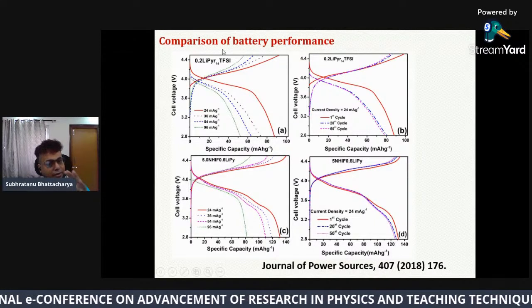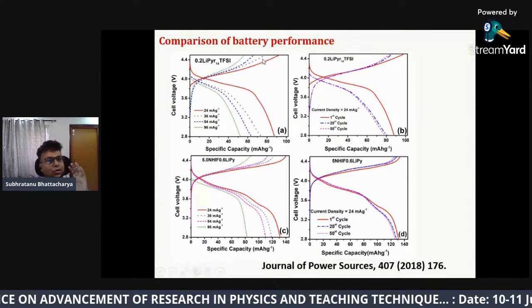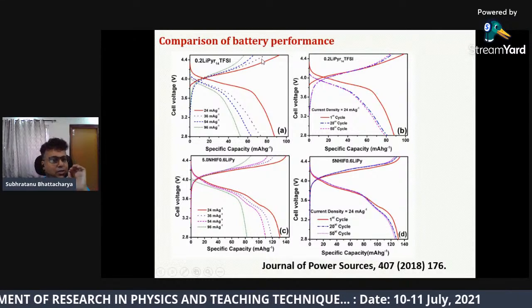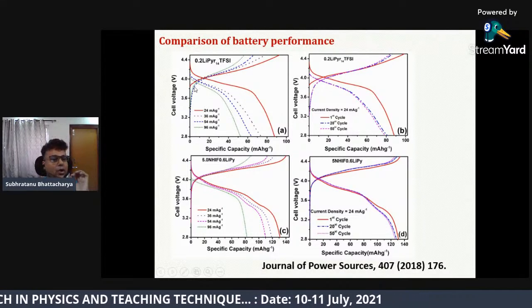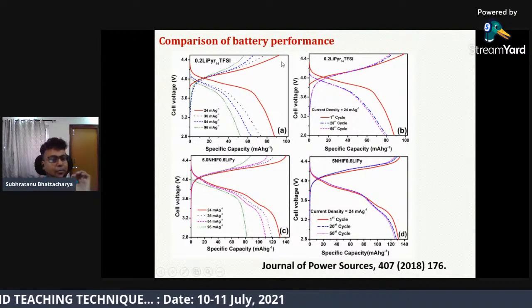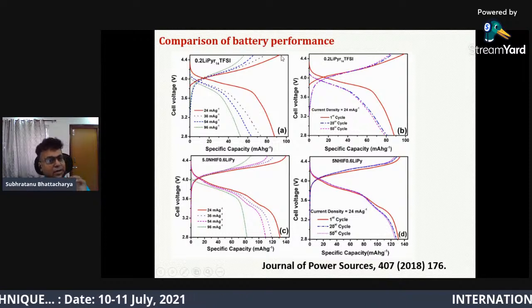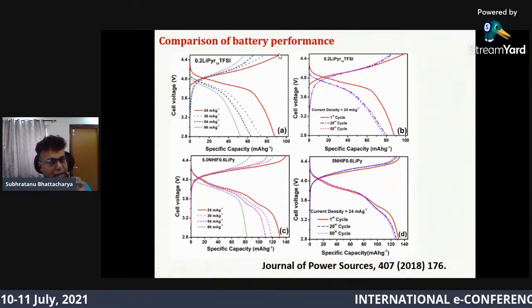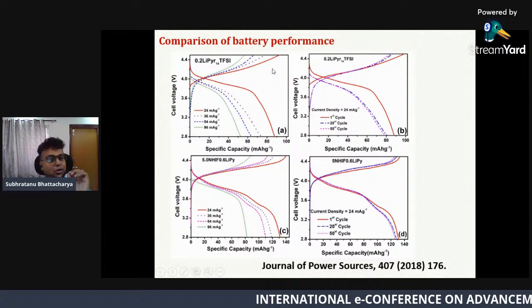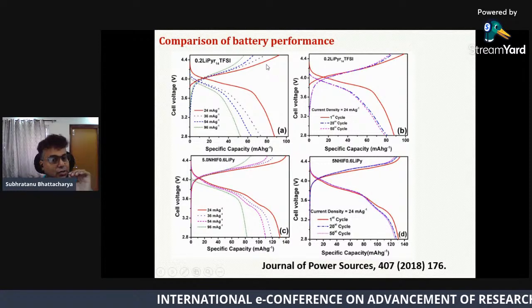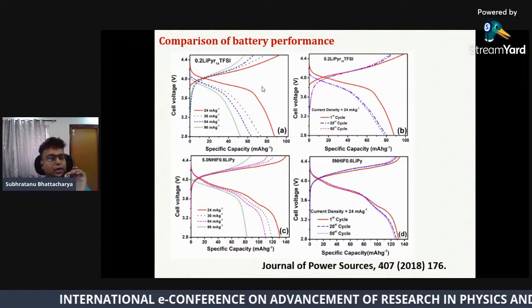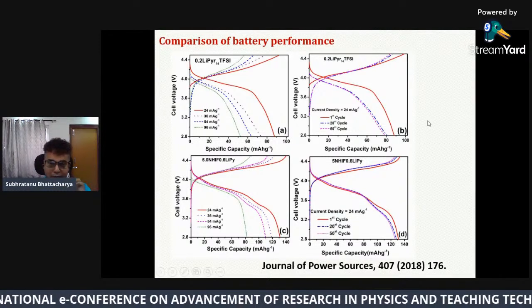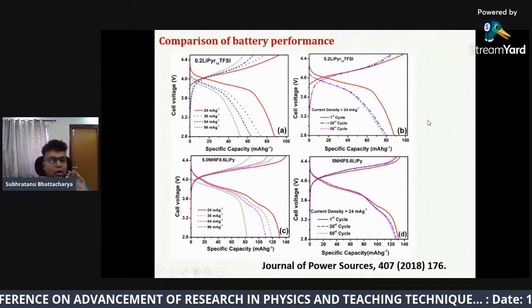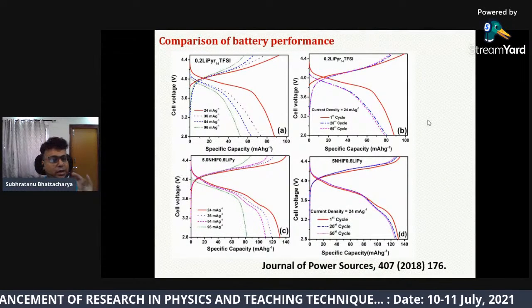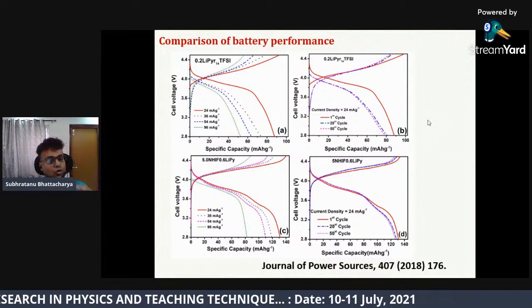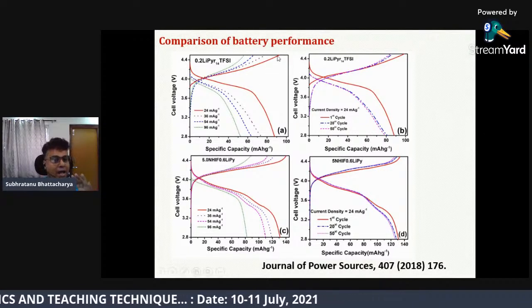Even at high discharge current, you are also not getting the capacity you should achieve. You can only achieve capacity near the theoretical capacity if you charge or discharge at a very slow rate, because of your low lithium transference number. So the only way to improve it is to increase the lithium transference number so that you can get high capacity